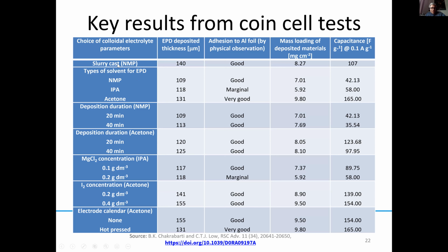So taking on from the slurry casting procedure of preparing electrodes for supercapacitors, NMP was used, with PVDF and carbon black, and we tried to see how that performance was. So the performance parameters we were testing against was thickness. Within industries, a good thickness should be between 50 to 200 microns. And the other thing is about the adhesion, does the material stick to the surface. Obviously slurry cast procedure sticks very well, so it's a well proven standard, but EPD doesn't always stick very well onto the surface of the aluminum foil, so we had to test that as well.